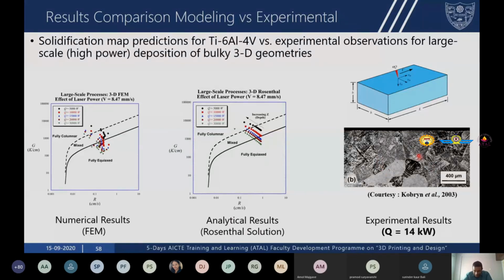Here you have an equiaxed microstructure at the surface, and you have a columnar microstructure through the deposit. So this is showing the possibility of a graded microstructure through the depth of the deposit. And here again, the modeling results are showing an equiaxed microstructure at the surface and a columnar microstructure at the bottom and a mixed morphology in the center. So the results from computational modeling are in good agreement with those obtained from experimental results.